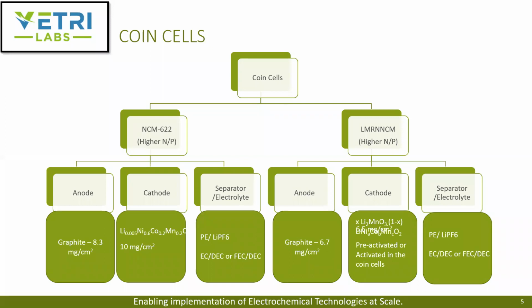For the separator electrolyte, they stick with a similar composition as the NCM material. The only difference here is the amount of oxygen available between the NCM and the lithium manganese rich NCM materials.